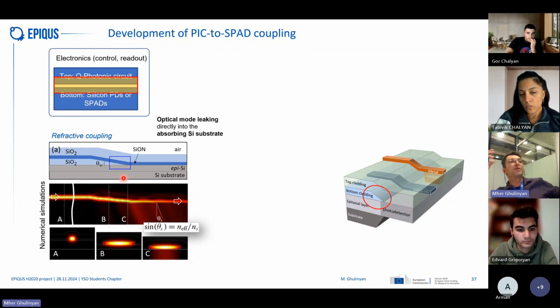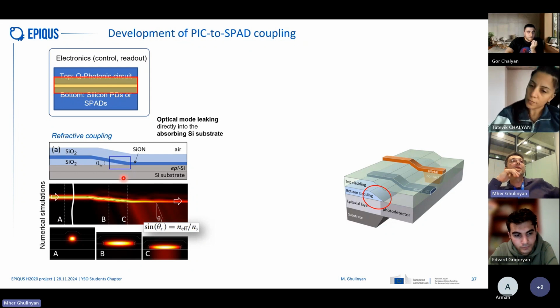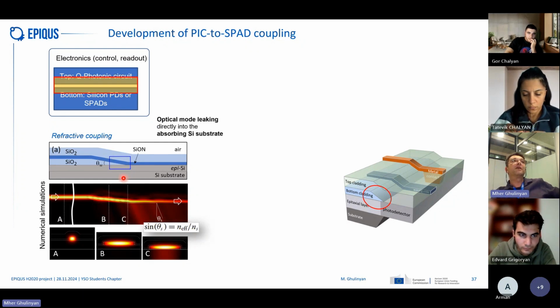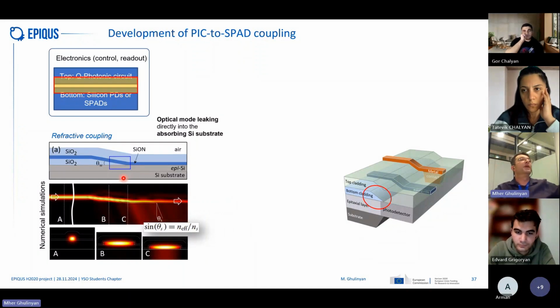And smooth surfaces in microtechnology are typically created when you realize, let's say, chemical wet etching of a material. Dry etching is a bombardment with ions, which have very high radio frequency plasma energy, and you create a lot of roughness on the surface. Wet etching is very smooth because it reacts at the atomic level with your material and removes it.